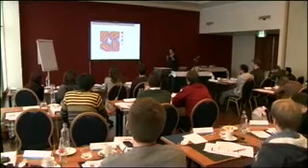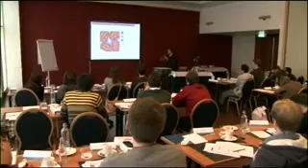As I said earlier, I think the main point of controversy depends on whether these little nanocrystalline areas are joined together or not. And clearly that is going to have an important effect on a lot of properties. But nevertheless, there is the existence of these different sorts of water with no clear division between them. Because if you do a drying experiment, you're going to progressively lose, first of all, the water that's in the bigger pores and then get to this layer here. But at the same time, you're going to start to be losing water from this interlayer. So it's very, very difficult experimentally, and this is the reason why there's so much uncertainty on the structure, to cleanly divide these different types of water.